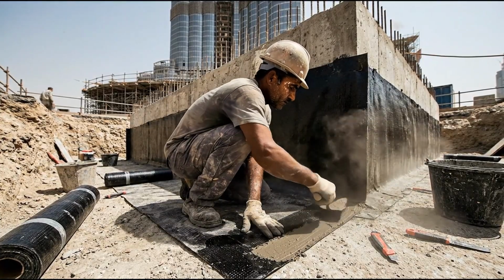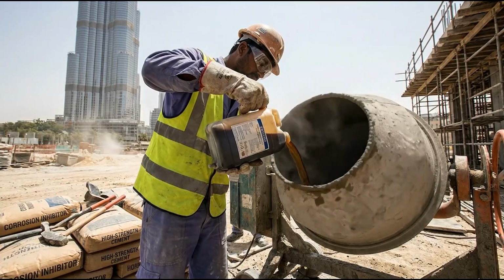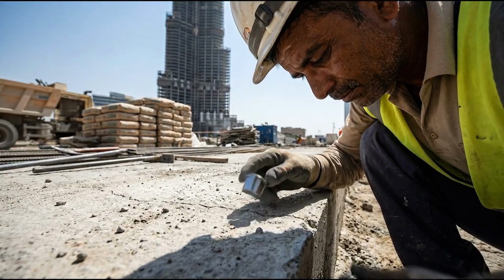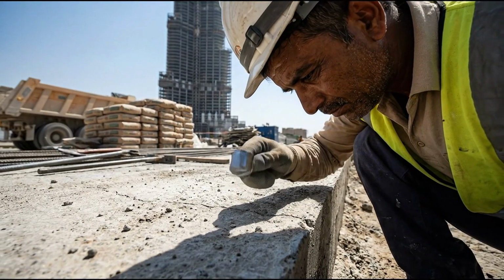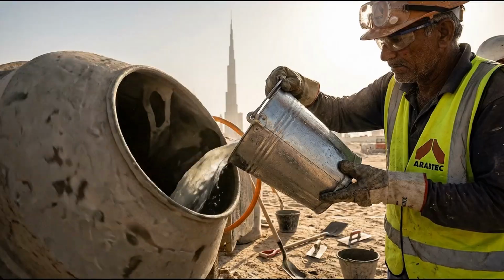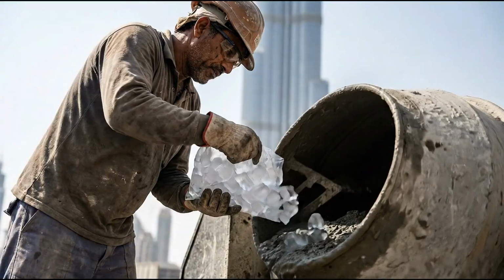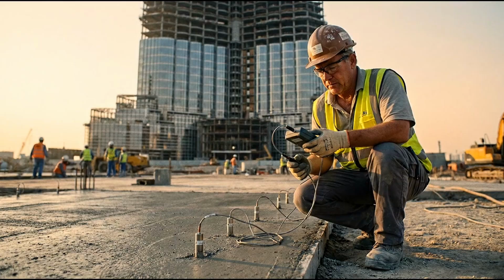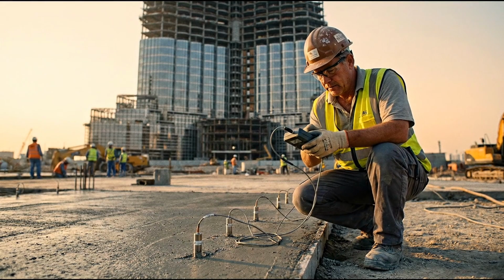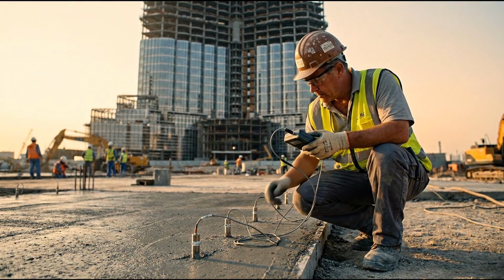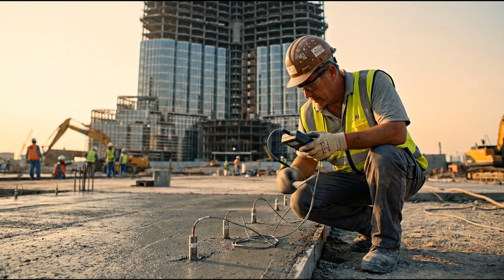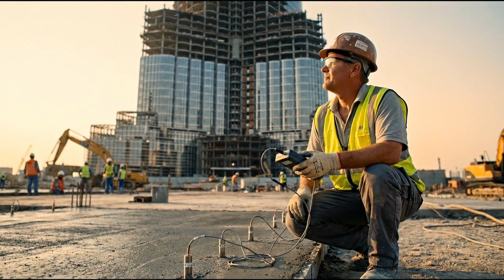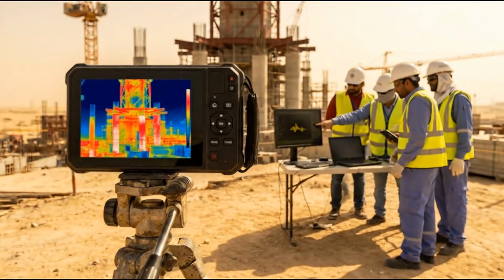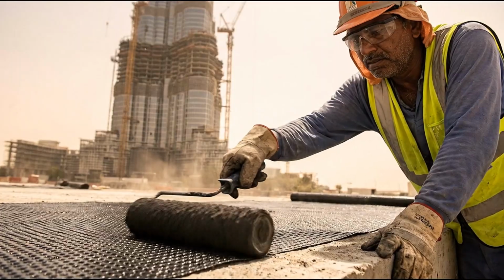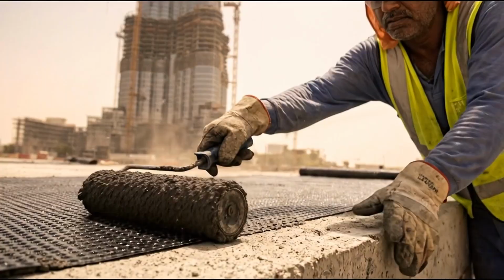The heat was the other enemy. Dubai in summer is brutal, and concrete in extreme temperatures cures too fast, which causes cracking. The team chilled the mixing water, used ice in the concrete mix, and poured during nighttime hours whenever possible. Temperature sensors were embedded throughout the slab to monitor the curing process in real time. Engineers watched the heat signatures around the clock, ready to intervene if any section began to overheat.